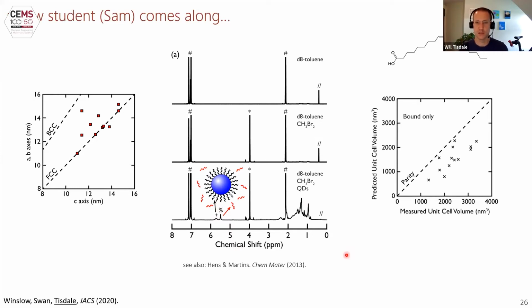And so Sam, using this information, turned back to his GISAXS data, and you can measure the volume of the unit cell very accurately using X-ray scattering. And then based on everything that's in there, he predicted what the unit cell volume would be. And the really interesting thing is that he only got good agreement between his predictions and the measured unit cell volume if he included the free ligand in the superlattice structure. And so based on this comparison, Sam concluded that the free ligand is not getting expelled into a separate phase, but is somehow getting entrained in the nanocrystal superlattice and is occupying space in the superlattice as another constituent.